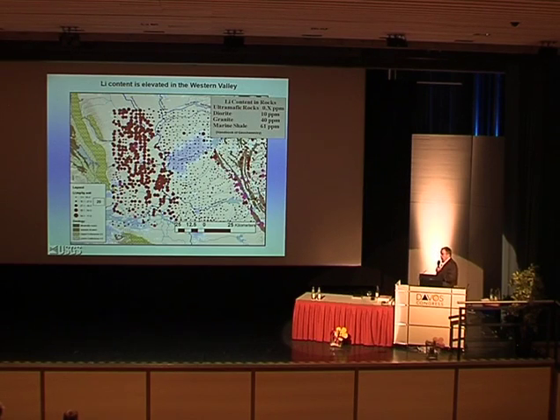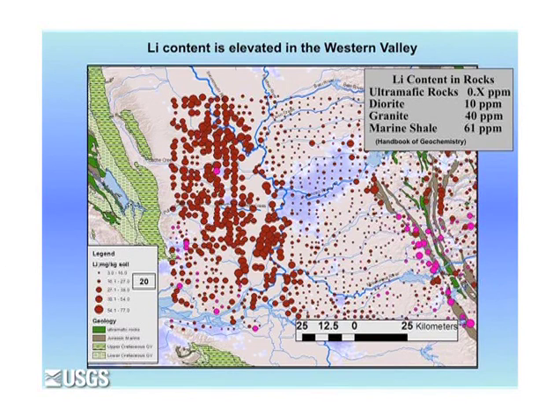So let's talk about the western side of the valley and how it's achieved its composition. So this is a map of lithium. Again, it's one of these proportional symbol plots. The smallest symbol is 3 to 15 milligrams per kilogram of lithium. The largest one is 54 to 77. Clearly, there's a segregation of high values on the west side of the valley.